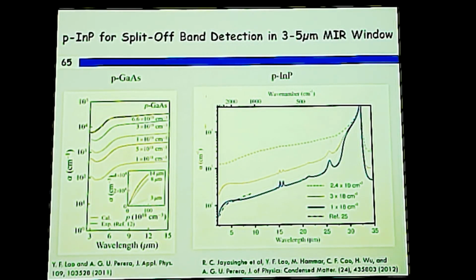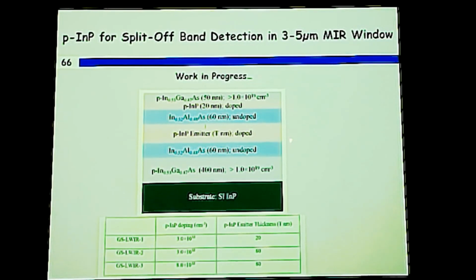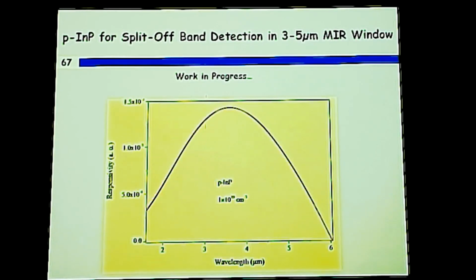That's the reason. Looking at the absorption of another material, p-type indium phosphide actually has a peak in the 3 to 5 range. So we are interested in this material system, and currently we have devices under production based on p-type indium phosphide. We have 3 devices, and based on the absorption properties, this is the simulated photoresponse, and we expect a 3 to 5 full width at half maximum band based on this p-type indium phosphide. The device is currently under production.